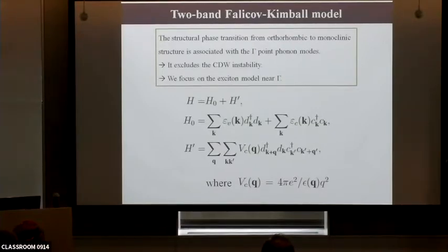Tantalum nickel selenide shows a structural phase transition from orthorhombic to monoclinic upon cooling, and this structural phase transition is associated with the gamma point phonon mode only. So it excludes the CDW transition. Therefore, we focus on the excitonic model near the gamma point.